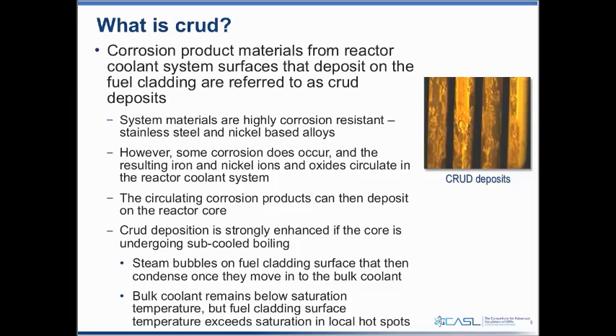We make all of the primary circuit out of highly corrosion resistant material, typically stainless steel 304 for the piping and reactor internals, and nickel-based alloys for the steam generator tubes. As mentioned, they're highly corrosion resistant, but some small amount of corrosion does occur, and a fraction of the material that corrodes gets released into the coolant and circulates around the primary circuit. That can then become available to deposit on the cladding surfaces too.